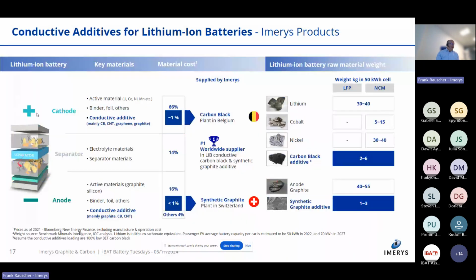And here you see again a cross section of a lithium-ion battery. On the left side, cathode, separator, anode. On the cathode side, we talked about the active materials. You have in the cathode, of course, also a binder and a conductive additive. It's mainly carbon black today, but you can also use carbon nanotubes, CNT, graphene, or graphite.